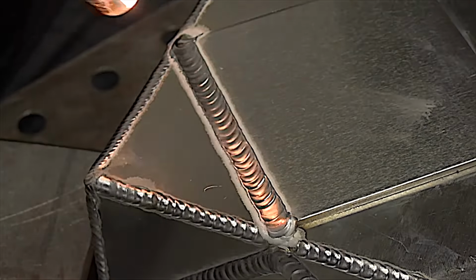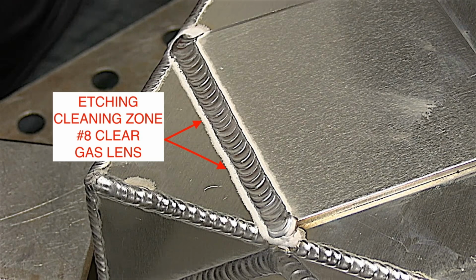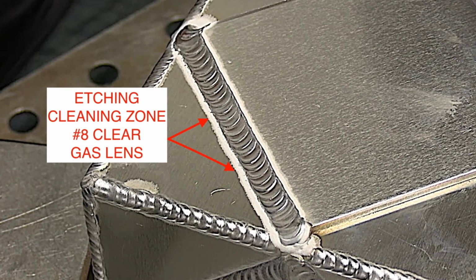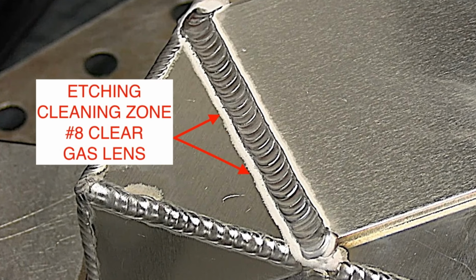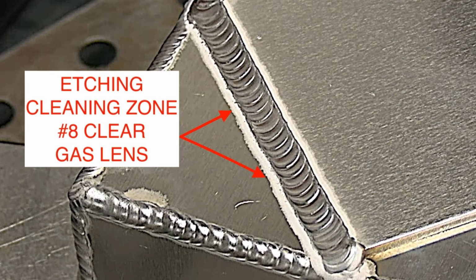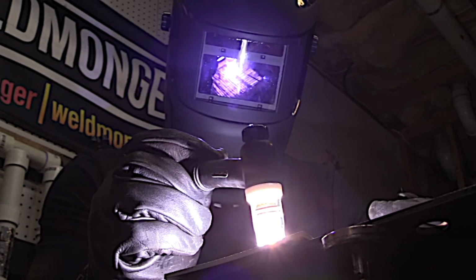Getting to the end here, I'm going to swirl this arc around a little bit so as to try not to leave any crater holes or anything like that. You can see a little bit of fine porosity try to rear its ugly head. That's pretty typical with aluminum. Again, this weld looks just about like the one with the number 5 cup, but it's got a lot wider etch zone.